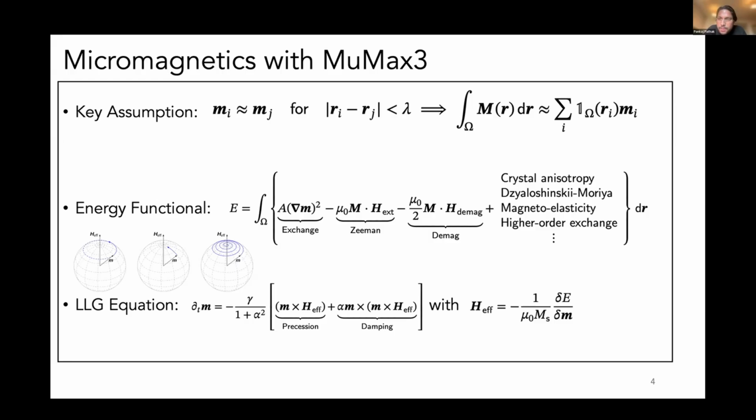So these are generally ground state simulations. So we basically ignore temperature and we say that if we have a very strong damping constant, we force the spins to relax to the effective field due to the interactions by the other micromagnetic cells in the simulation. So there is no temperature in these simulations yet. However, this behavior is not expected to change significantly with temperature, because experimentally what we find is that, as long as you're under the Curie limit for this material, this lattice reorganization still takes place.